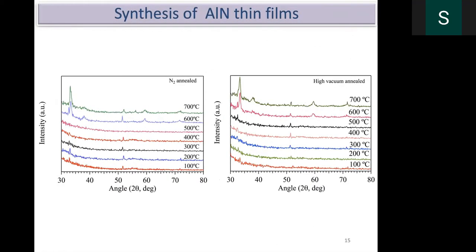But how we arrived at 800 degrees centigrade can be seen from this. Nitrogen annealed and high vacuum annealed separately. We took the amorphous film and annealed at different temperatures. You can see up to 500 degrees centigrade, there is no change in the system. You know, the melting point of aluminum nitride is more than 2000 degrees centigrade, so there will not be any change in the system.